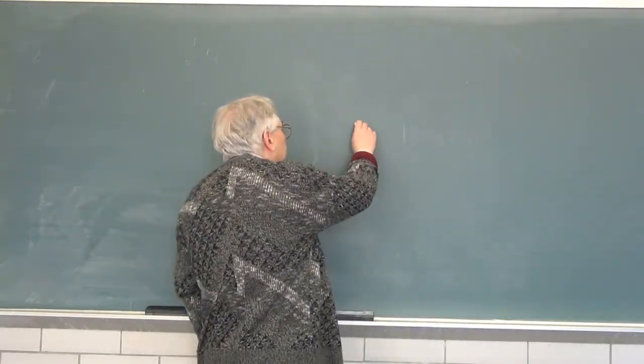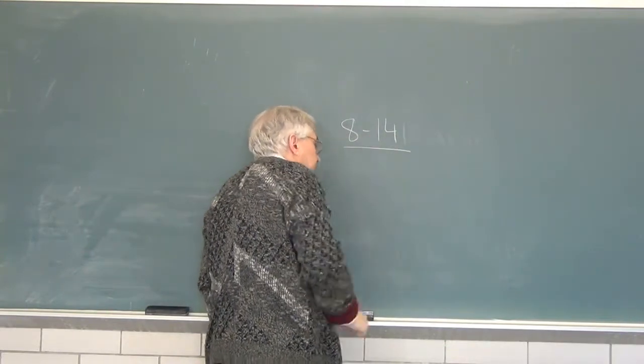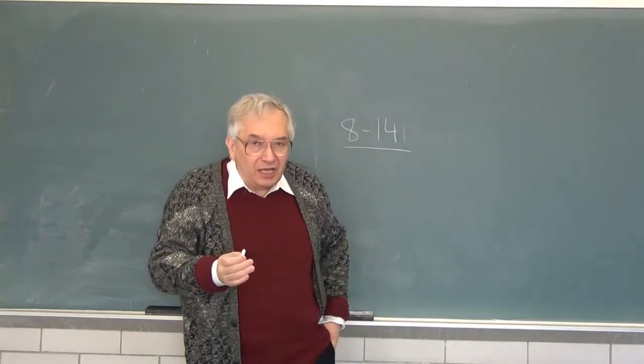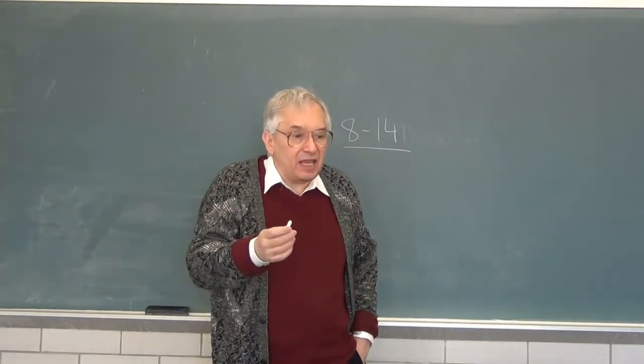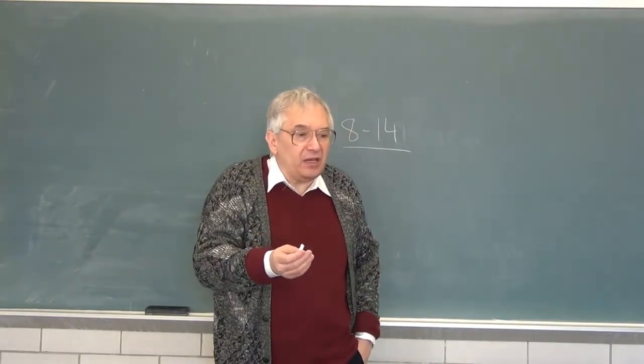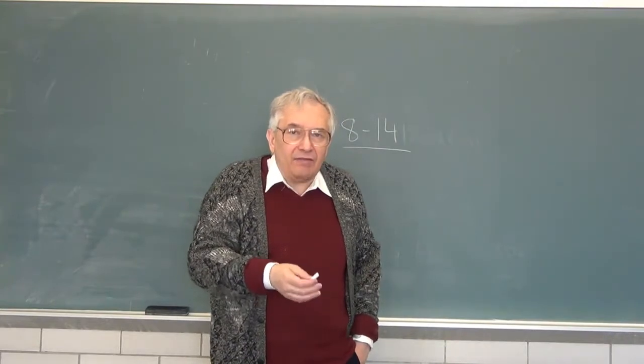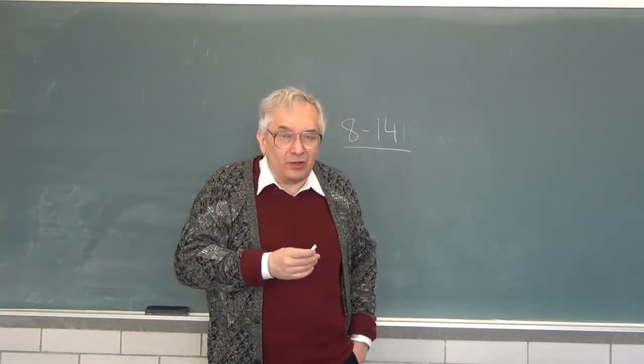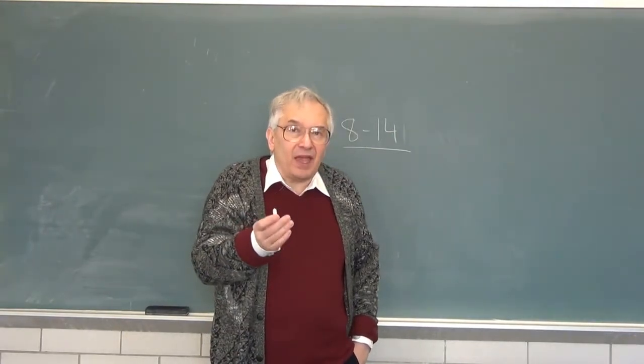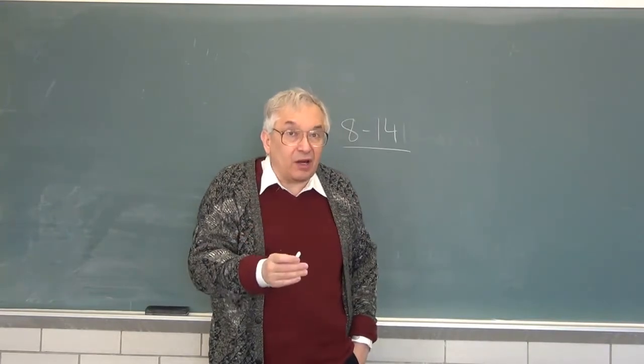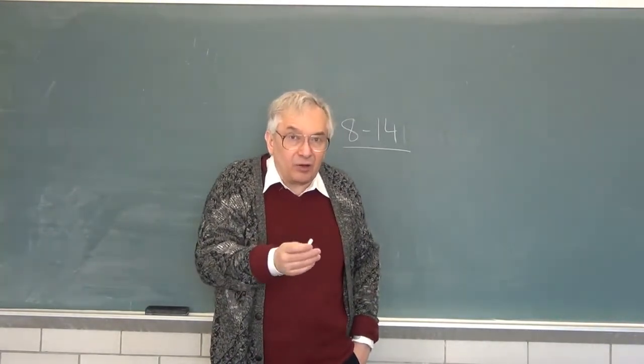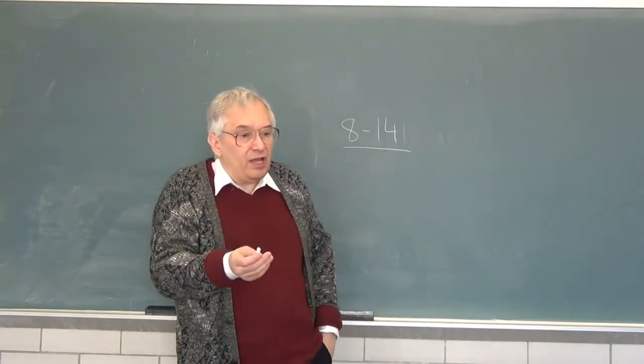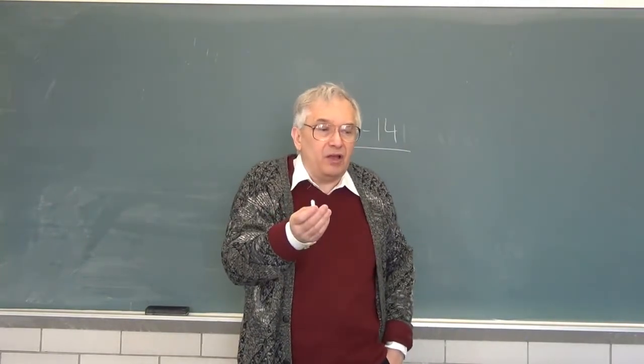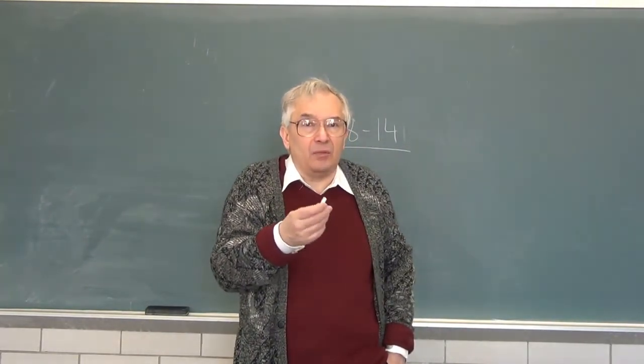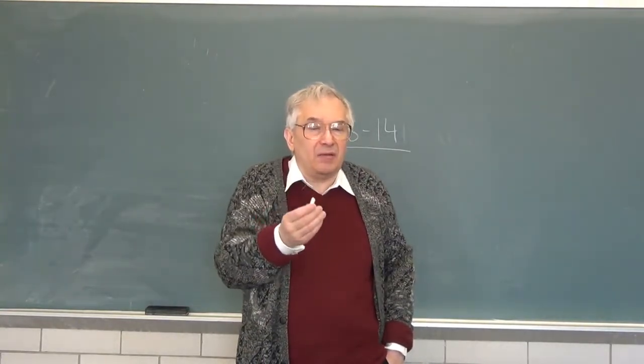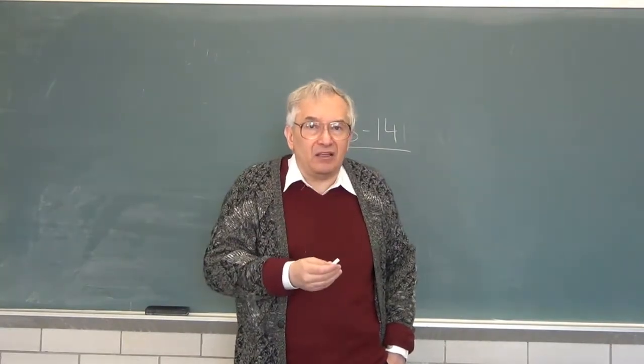Let's jump ahead. The jump ahead is to figure 8-14. 8-14 is a composite. There are actually four pieces, A, B, C, D. And in addition to there being composite pieces, A, B, C, D, I've used tricks with displacing one vertical axis relative to the other, so that, in fact, there are more than four chemical systems represented there. So there is a huge amount of measurement, a great deal of work by a bunch of different people, all on the same graph. And in fact, in particular, you see measurements of polystyrene in carbon tetrachloride and perdeuterobenzene. You see measurements on polydimethyl siloxane. You see measurements on polyethylene oxide in water.